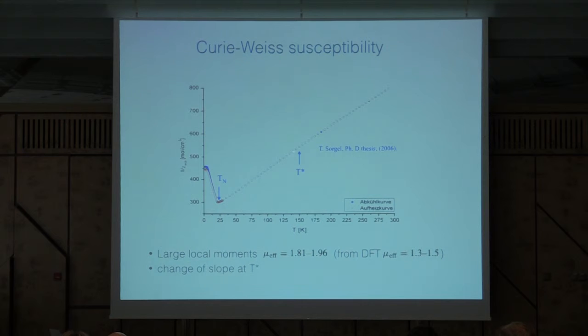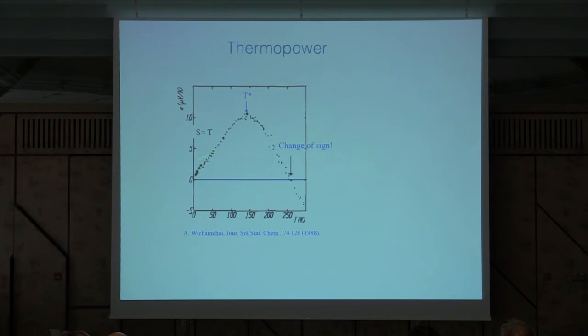You don't see it here, but first of all, if you do fits to the susceptibility, you extract quite large values of the local moment. And trust me, there is a very slight change of slope here at the same temperature where there is an anomaly in the resistivity. The thermopower is also anomalous. It starts like a good Fermi liquid, and then it saturates and even changes sign. So this is really close to what is expected for correlated systems.